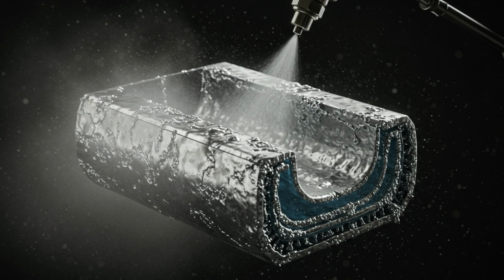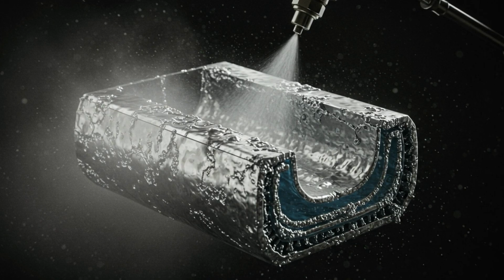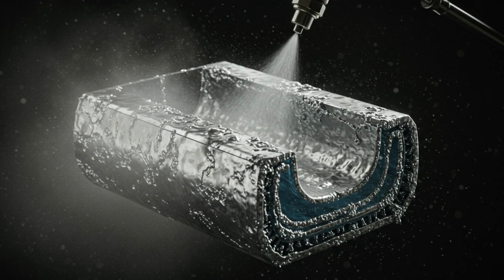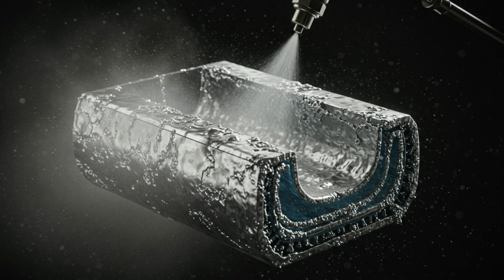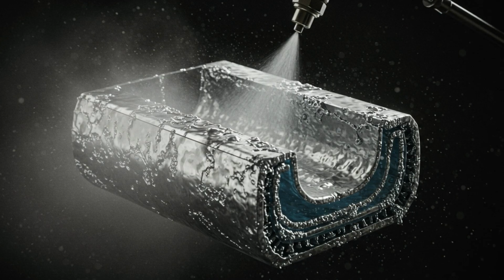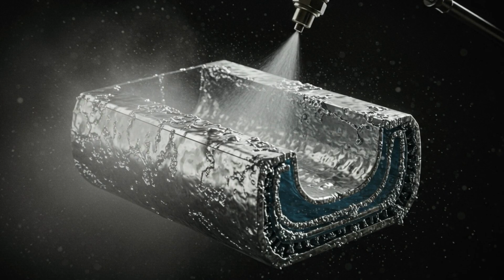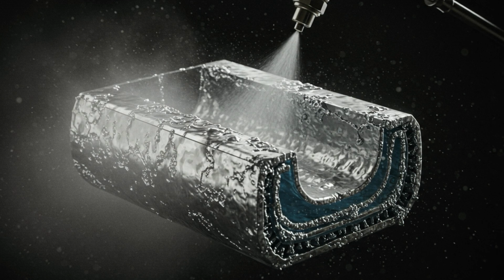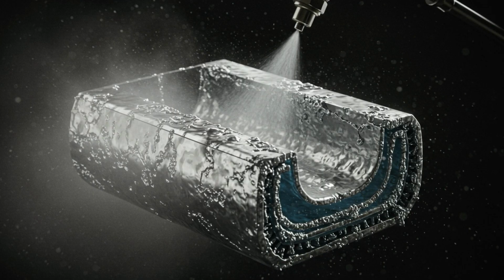Now comes the magic. A solution of silver nitrate is sprayed onto the glass. Through a chemical reduction reaction, the silver atoms precipitate out of the liquid and bond to the glass surface, creating a layer only a few atoms thick. To protect this precious silver from oxidation, which would turn it black over time, a layer of copper is often deposited over it, followed by multiple coats of moisture-resistant paint. The result is a surface so smooth that it reflects light with nearly 95% efficiency. You are no longer looking at glass. You are looking at a high-performance optical instrument built from sand, tin, and silver.